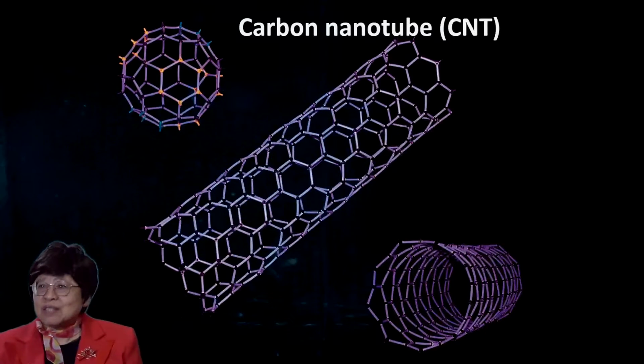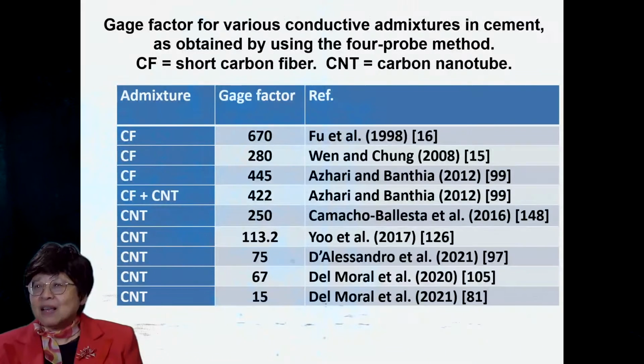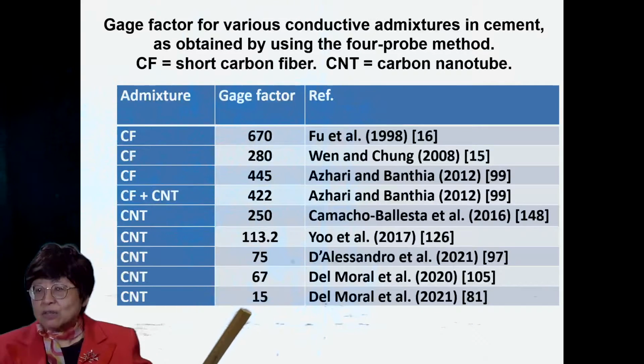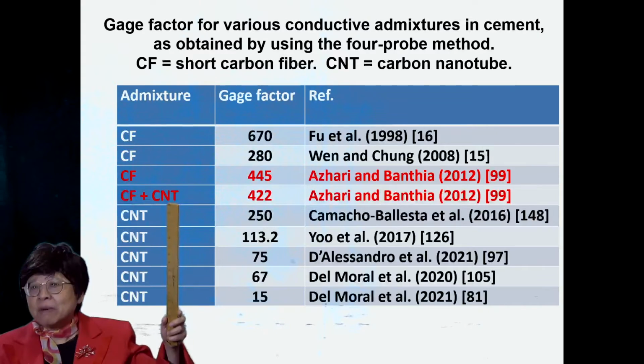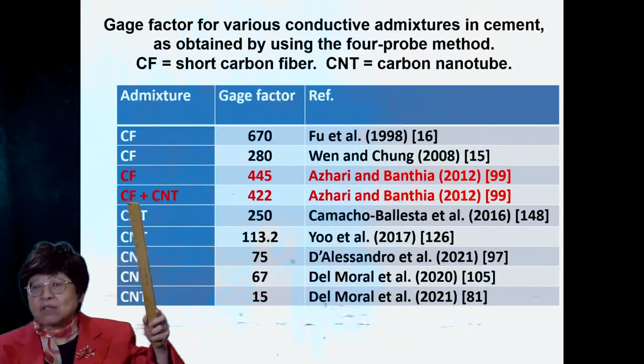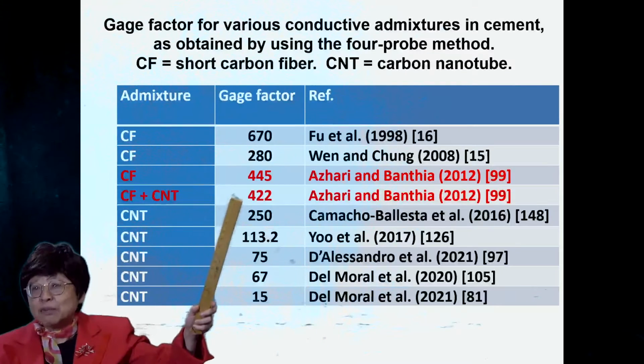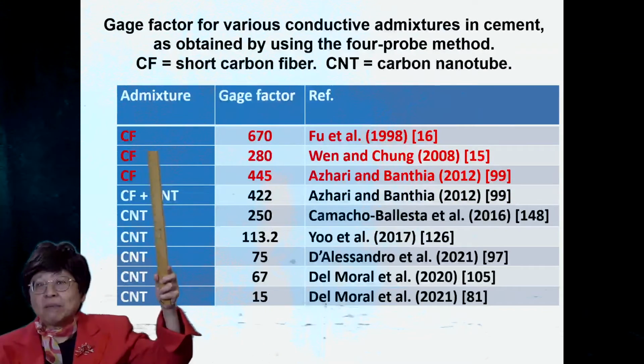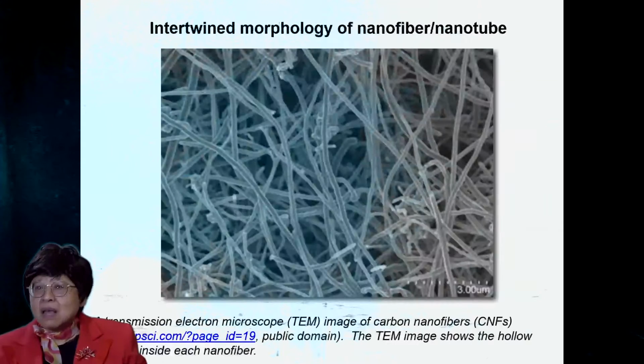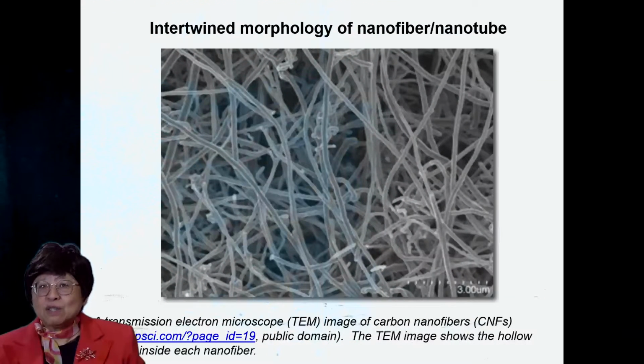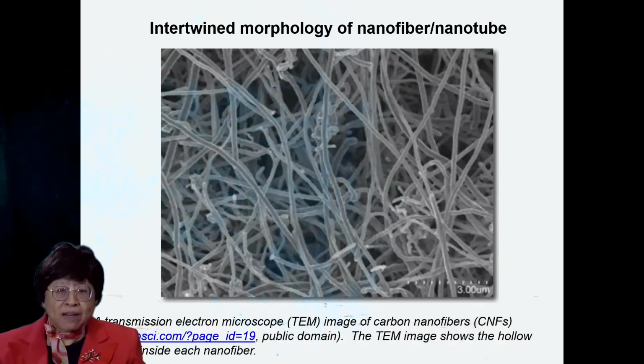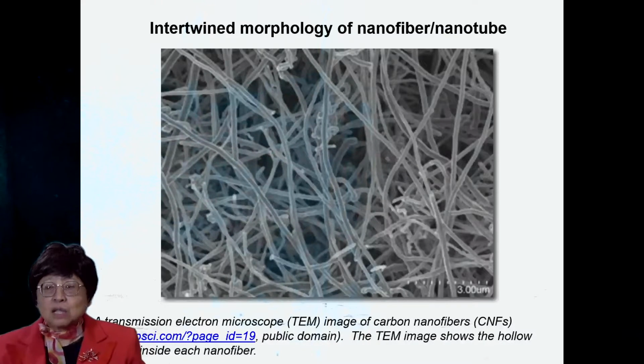Now, there's a big interest in using carbon nanotube in composites. We have looked at the effect of adding carbon nanotube to cement in terms of the piezoresistivity as described by the gauge factor. And you can see that adding carbon nanotube, CNT, to the short carbon fiber, CF, doesn't improve anything. In fact, the gauge factor decreases. The winners are still the carbon fiber, no carbon nanotube at all. The reason for the carbon nanotube not helping that much is their intertwined morphology, making the dispersion of the carbon nanotube not easy.